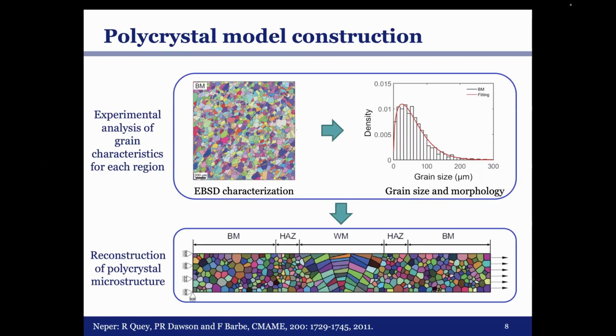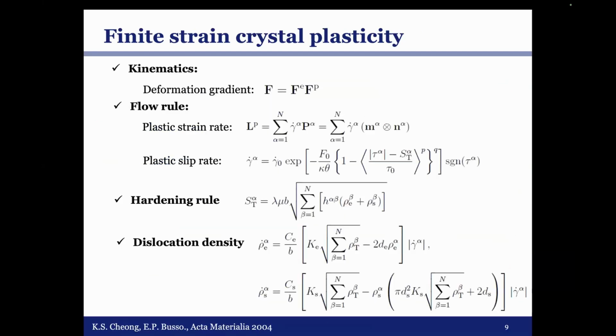Following this approach, we first need to construct such a microstructure model. So we do EBSD measurements to get the statistics of the grain size distribution information, as well as the grain orientation distribution. And based on this information, we construct such a microstructure model considering grain size distribution using software named Neper. And then we use the single crystal plasticity model to do simulations. The model that we used is quite classical. I won't go into details of these equations. What I just want to emphasize is that we use the same model for different regions of the specimen, but with different parameter values.